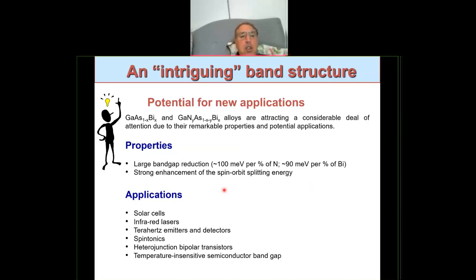So what we found is that if you take gallium arsenide with bismuth or gallium arsenide with nitrogen, the band gap of gallium arsenide will decrease by 100 meV for every % of nitrogen. So for example, if you've got gallium arsenide at 1.4 eV, if you only put in 4% of nitrogen, you can decrease by 400 meV, so that you reach 1 eV. And bismuth decreases at a similar rate, about 90 meV per % of bismuth. So you don't need a lot of bismuth or a lot of nitrogen, and hopefully you can keep that lattice constant, practically just using gallium arsenide with a small amount of nitrogen and a small amount of bismuth. And of course, the applications are quite numerous, but I was just concerned with the solar cell 1 eV material for the time being.